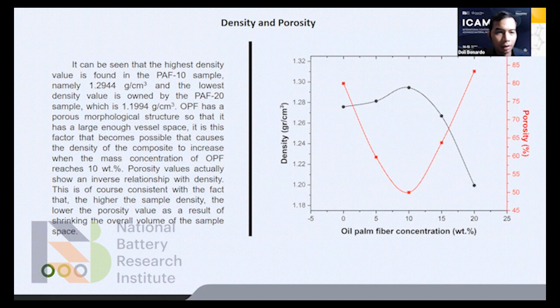OPF has a porous morphological structure so that it has enough interfacial space. It is possible that this factor causes the density of the composite to increase when the mass concentration of OPF reaches 10 weight percent. Porosity values actually show an inverse relation with density. This is consistent with the fact that the higher the sample density, the lower the porosity value as a result of shrinking the overall volume of the sample.